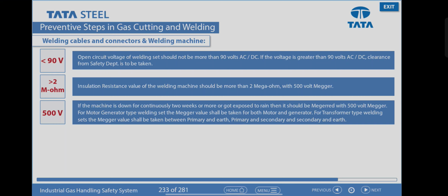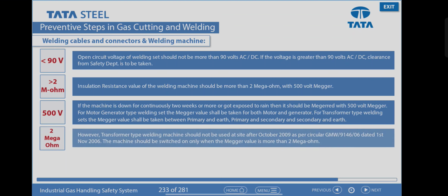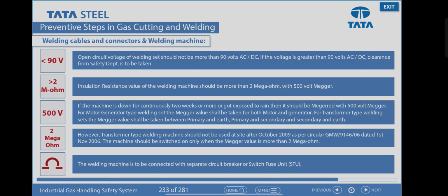For motor generator type welding sets, the megger value shall be taken for both motor and generator. For transformer type welding sets, the megger value should be taken between primary and earth, primary and secondary, and secondary and earth. However, transformer type welding machines should not be used at site after October 2009 as per Circular GMW/9146/06 dated November 1st, 2006. The machine should be switched on only when the megger value is more than 2 megaohm. The welding machine is to be connected with a separate circuit breaker or switch fuse unit, SFU.